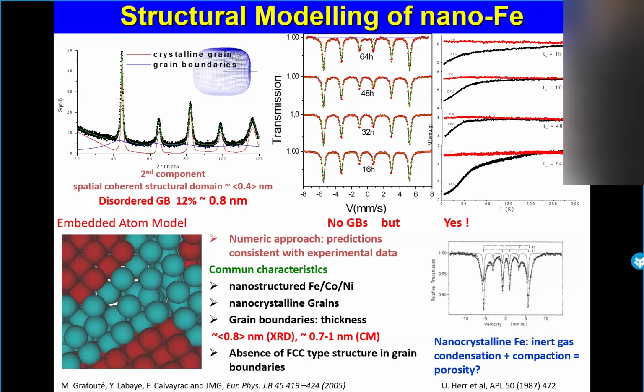And the main conclusion also was that there was no FCC phase, as was predicted by other groups. And now it was possible to explain that the small differences between the structure within the grain boundaries and the grain could explain why it was difficult to see two components in the Mössbauer spectra.